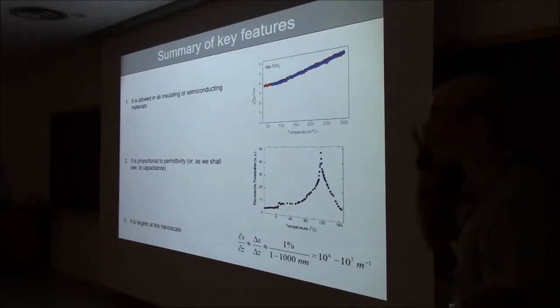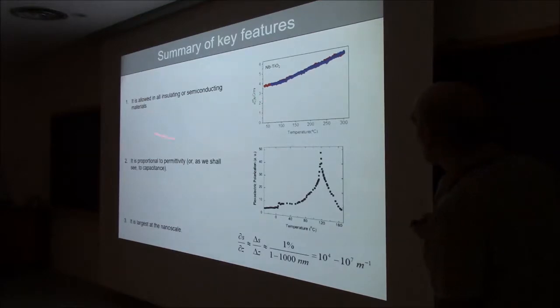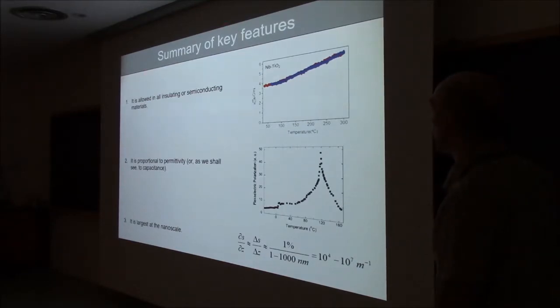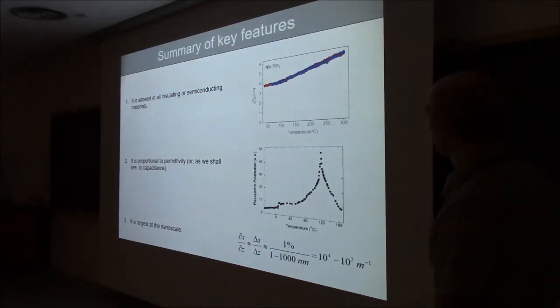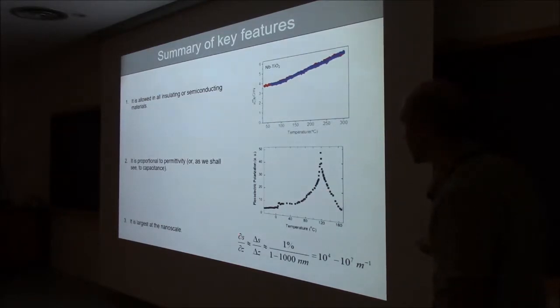So this is more or less the summary of the physics that you absolutely need to know of flexoelectricity. That it's allowed both in insulating and semiconducting materials and irrespective of whether your material is centrosymmetric or not, so it is quite universal. And it is the strain gradient that allows you to extract polarization even in centrosymmetric materials. That is proportional to dielectric constant, and therefore it will generally be big in materials with big dielectric constants, so ferroelectrics. And that its effects will be most dramatic at the nanoscale, purely because you can get bigger strain gradients. Right?